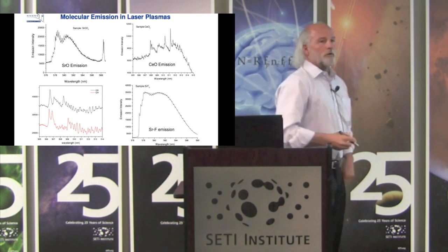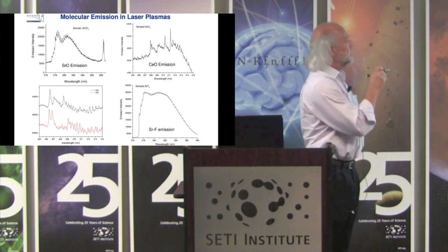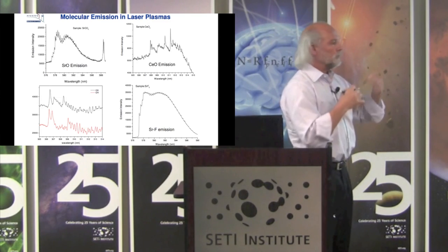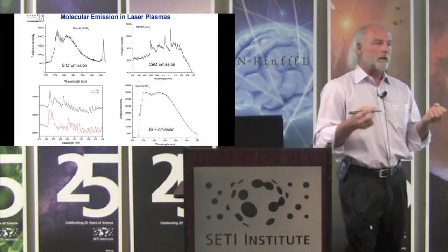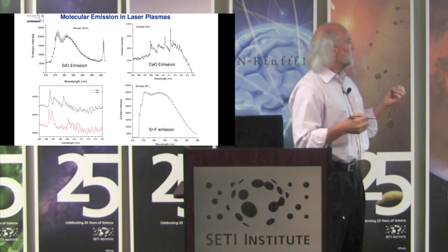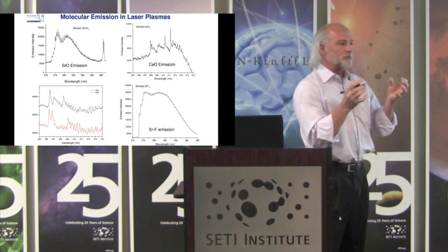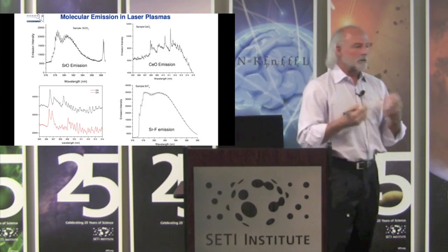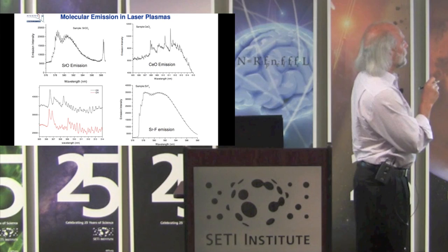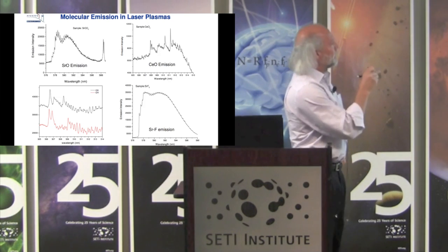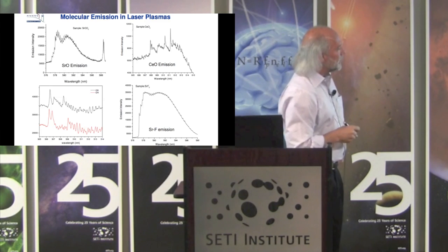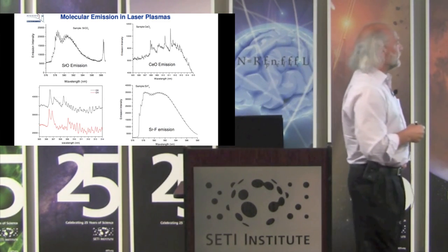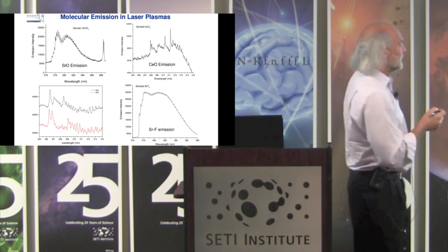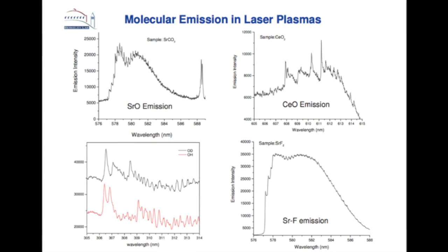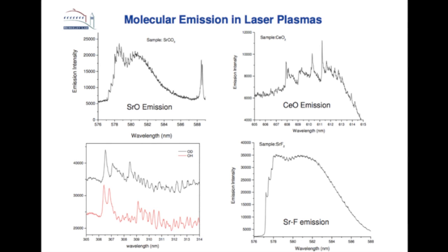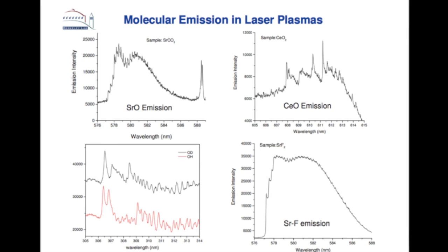This is something we ignored for a long time in LIBS plasmas. When these plasmas form in an atmosphere, and you rip everything off, you heat everything to where it's hot elemental species, strontium, cerium, whatever is in this plasma, and then it's in an oxygen environment, it collides with the oxygen, and as that plasma cools, it forms an oxide. So these spectra we've ignored for years because you look at that, it looks like noise, it looks like garbage. Well, the old cliche, one man's garbage is another man's gold. This is all vibrational rotational states of the molecule. So we were ignoring it for all these years, but there's tremendous information in these spectra.